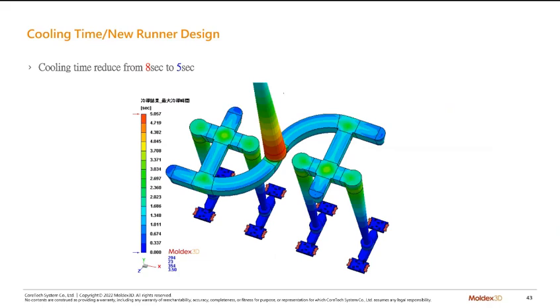when they do this kind of change, they also change the cross section of this runner to a smaller one. So it requires a shorter cooling time, and it is reduced from 8 seconds to 5 seconds. And for this kind of design, the whole process is 13 seconds. So if they reduce 3 seconds, it means they can produce like 20, maybe 25% more product in the same period of time.